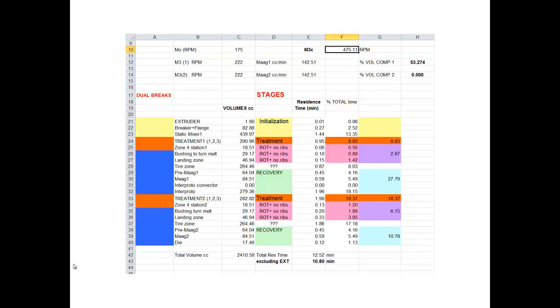But recovery is no treatment. There's just flow. So the melt is transported, being pushed, if you want, and is moving by just the pressure flow, which pushes the melt from the exit of the treatment zones towards the end of the machine. Okay, and we see that it's about 2.5 minutes for that time.